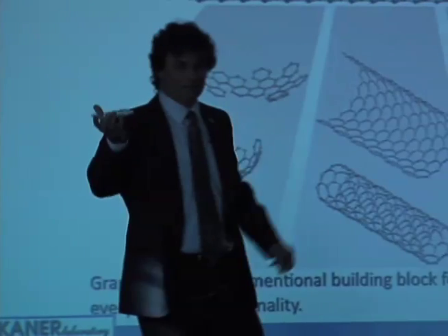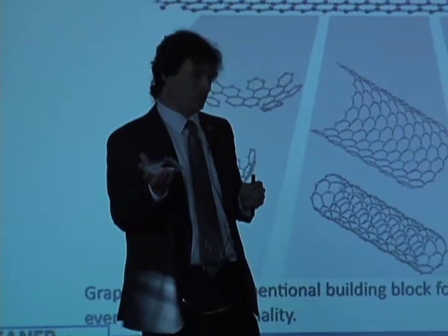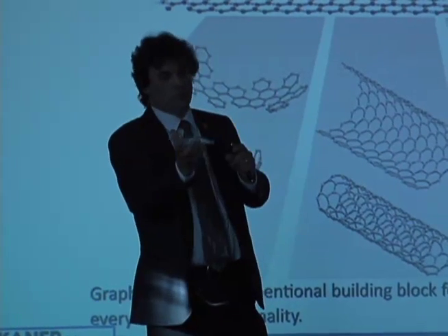But that actually wasn't the genius of Novoselov and Geim. The real genius is, how do you know you have a single layer? What they did is they took it and put it on a piece of silicon with a 300 nanometer oxide coating, and it forms a beautiful interference pattern. I'm going to pass this sample around. Almost all the samples I pass around you can touch, but my students would appreciate it if you don't touch this one because it's actually hard to reproduce. So just look at this, don't put your fingerprints on it.